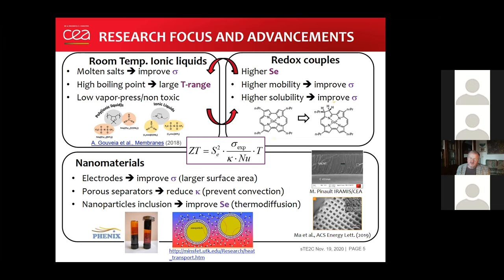And there is another important progress that has been made, which involves the use of nanomaterials, either as a part of the device component or part of the liquid itself. The first example is that of electrodes. By introducing nanostructured electrodes, we can increase the active surface area of electrodes and therefore the electrical resistance will be reduced. Some people are also using nanoporous or microporous separators inside of the thermoelectric or thermogalvanic cells to prevent convective movements of the liquid. This would reduce the thermal conductivity.